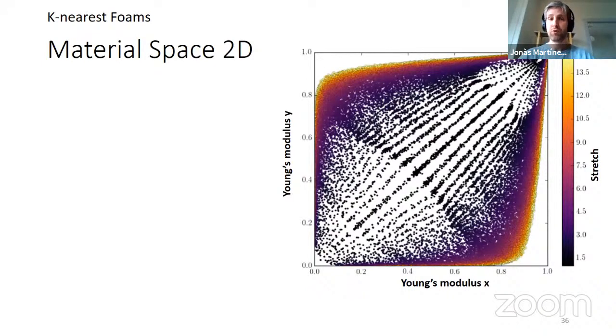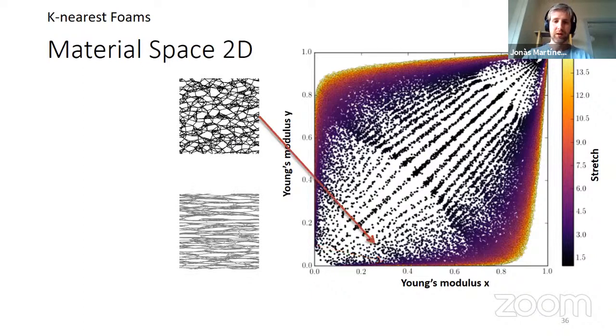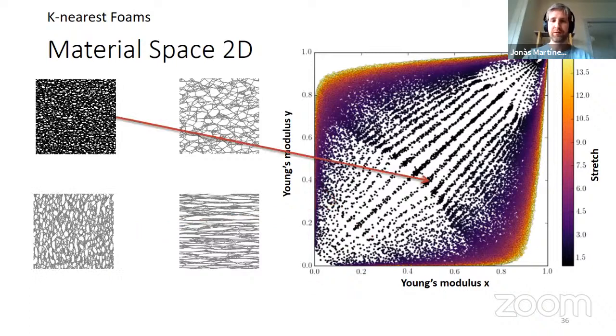Here, I'm going to show you the material space in 2D. In 2D, we span a quite wide space of Young's moduli, almost reaching the complete square, which would be the optimal bounds achieved by laminates, but we achieve something pretty close. And here you can see some samples of this space. Here you can see the Young's modulus in one direction and the Young's modulus in the other direction. The color is correlated with the stretching factor of your material. The more you stretch your material, the more extreme the contrast gets between one direction and the other.